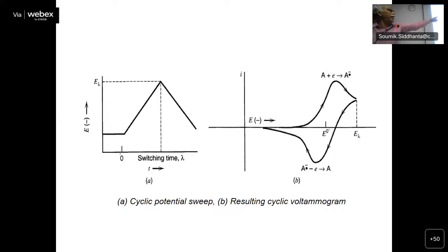That arrow is shown in a region corresponding to E0 prime, formal potential, E half. That is where the onset of the reaction happens. By the time you go to the peak, already the surface concentration is 0. So A plus e giving a radical anion, anthracene, naphthalene, that is the value. P corresponds to surface concentration of this as 0. And then there is a decrease. That decrease is exactly as predicted by the Cottrell equation. That means t to the power minus half dependence you will get.